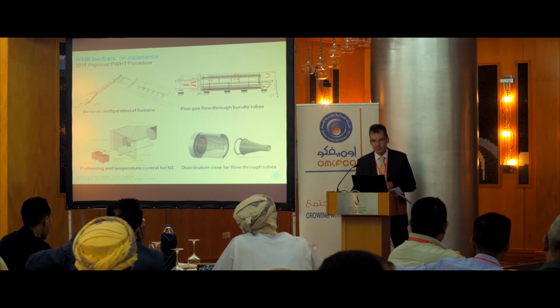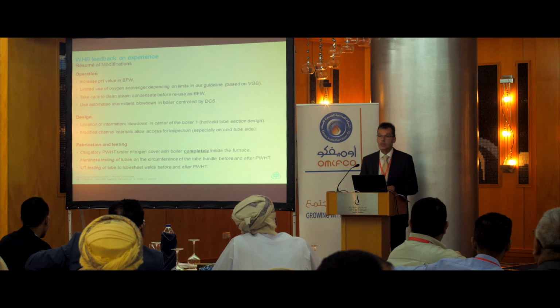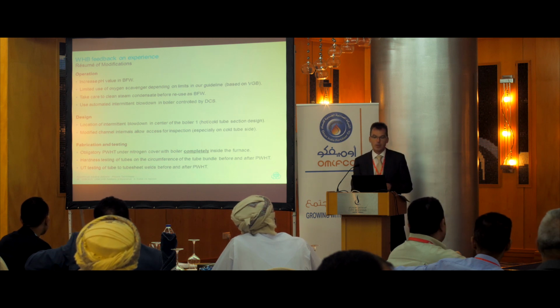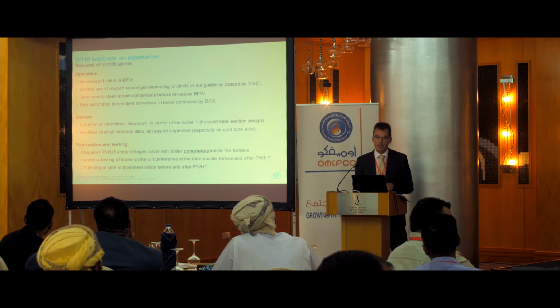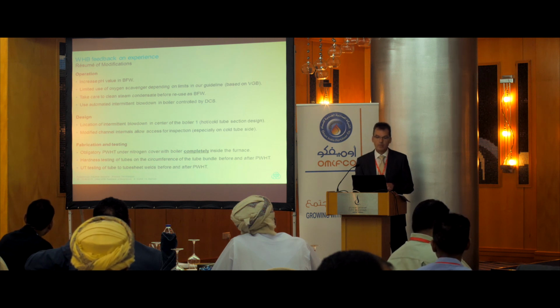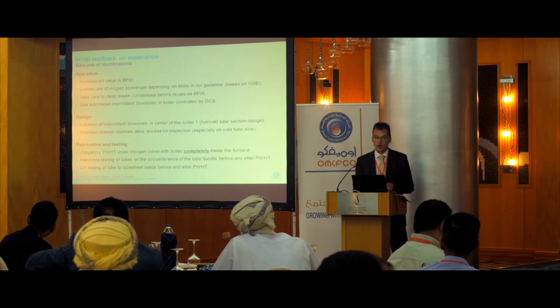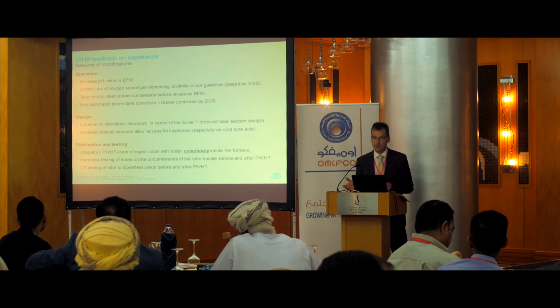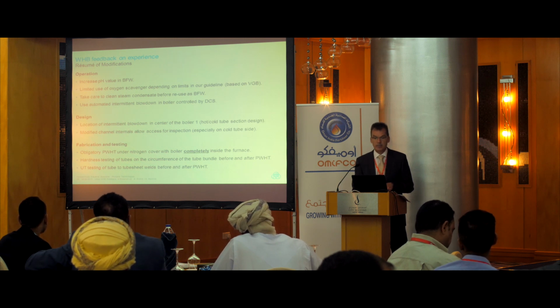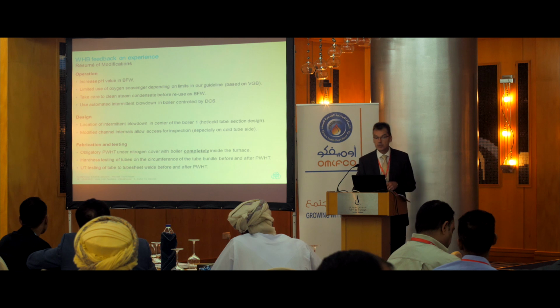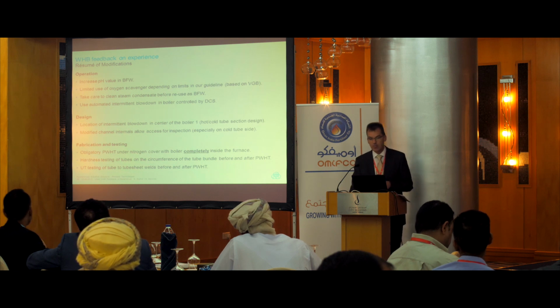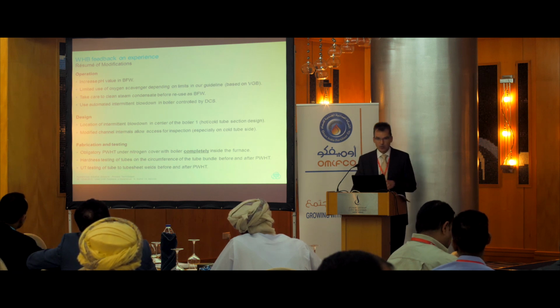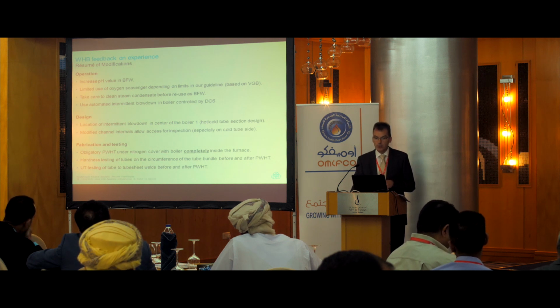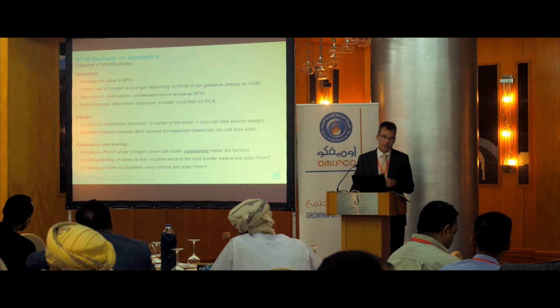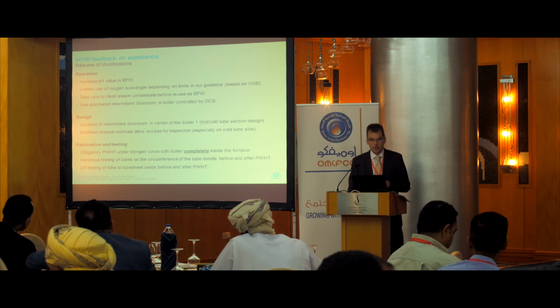Coming to my last slide, the resume of the modifications. In operation, increase the pH value in the boiler feed water, as mentioned before. Limit your use of oxygen scavenger, depending on limits in our guideline. Take care to clean condensate before reuse as boiler feed water. Don't make any reuse without proving where it is coming from. Use an automated intermediate blowdown in the boiler controlled by DCS. Don't rely on operational personnel.